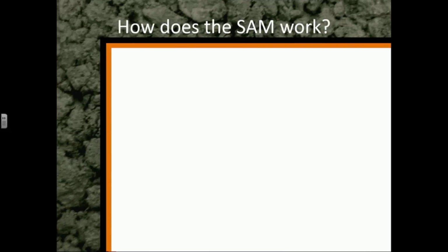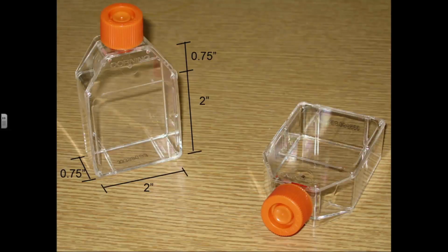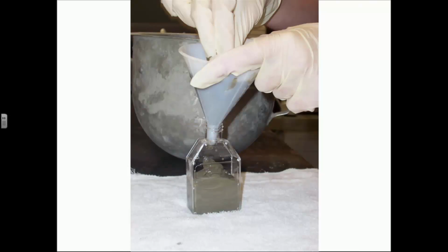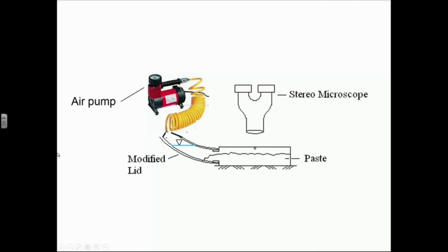How does it work? What's it all about? Well, to show you what it's about, I'm going to take these bottles that are about 3 inches tall, about 2 inches wide, and about 3/4 of an inch deep. And the cool thing is that they're optically clear. I can see through them. Okay? And we're going to fill them up full of air-entrained cement paste. Okay? And we're going to put some water on the top of them, tilt them over on their side, and this is the paste, and over time, bubbles are going to rise up and get caught on the bottom of the glass.